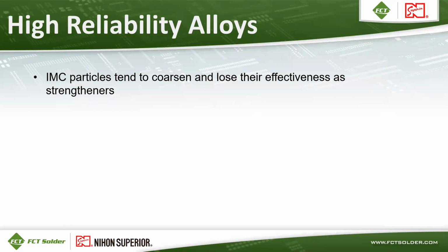The problem with that is when you have intermetallic compounds as your strengtheners in the solder, they tend to coarsen over time and they lose effectiveness, which we saw in the diagram with silver as an IMC particle strengthener. Silver lost effectiveness as we went to a more aggressive thermal cycle.